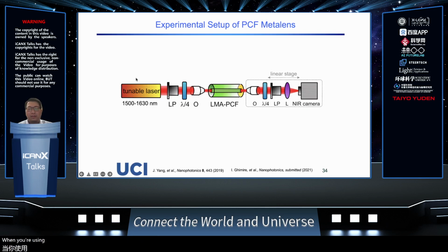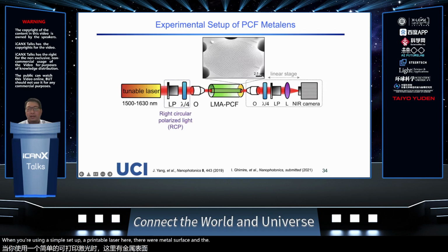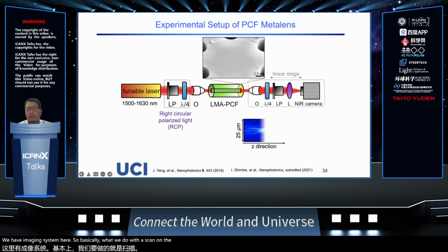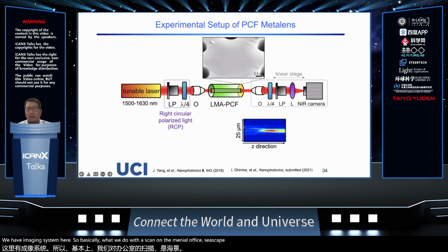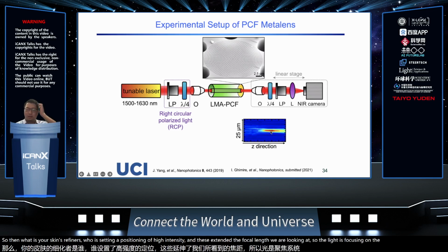We are using a simple setup. We have a tunable laser here. We have a metalens at the ends of the fiber, and we have an imaging system here. So basically what we do is scan on the linear stage. Once you scan, you find a certain position where you have a high intensity, and this is exactly the focal length we are looking at. So the light is focusing as a lens at this position.